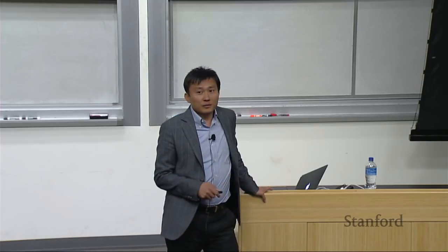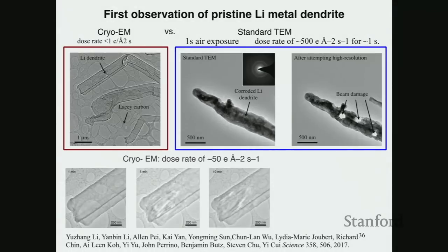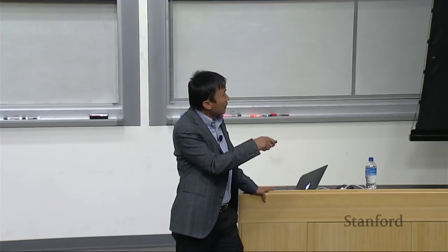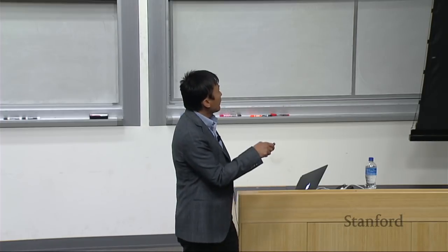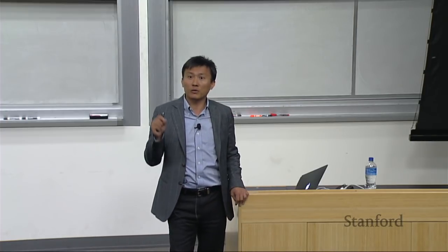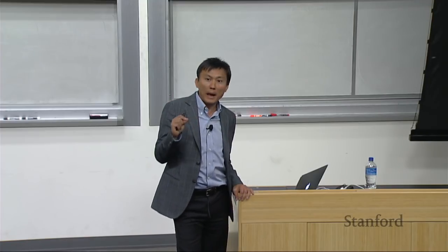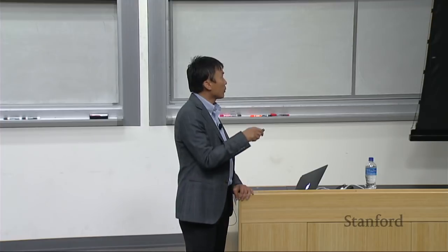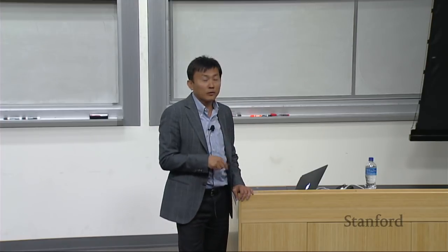So after several months, we had really surprising data. This is a lithium metal filament. Using this Cryo-EM technique, we could image it. In the past, as soon as you imaged your metallic lithium filament, it looked dark in color. The reason is this lithium metal already reacts with the moisture in the air, even with a second of exposure. And that's the end of the world, right? That will cause it to become black. Lithium metal should look like this, with very light contrast, because it's element number 3, with small atomic mass. It shouldn't have that much contrast under an electron microscope. And this has already become lithium oxide, lithium carbonate.